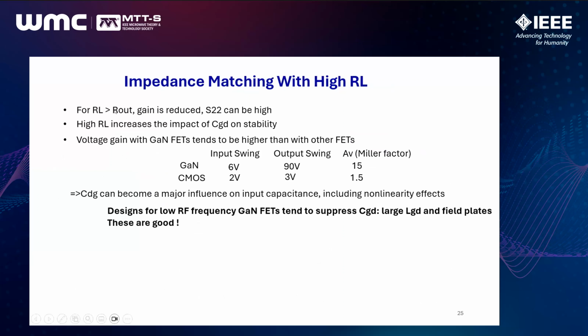If we apply RL greater than R out, then that reduces gain and can lead to high S22. High RL also increases the effect of CGD on stability. The voltage gain that you obtain with these FETs tends to be higher than with other FETs. For example, for gallium nitride with an input swing of 6 volts and an output swing of 90 volts, the Miller factor is about 15. By contrast, on the other extreme, for CMOS, you might have a 2-volt input swing and 3-volt output swing, leading to a Miller factor that's 10 times lower.